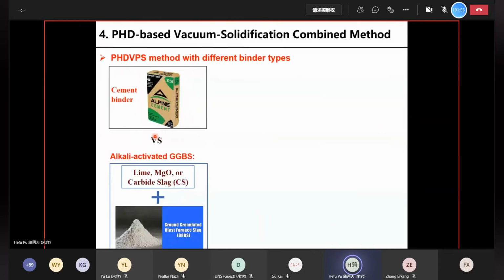We also look at different binder types. We compared the traditional cement binder with the alkaline activated GGBS, which is a ground granulated blast furnace slag. We use different types of alkalines such as lime, MgO, magnesium oxide, and carbide slag. The alkaline activated GGBS has better performance than the traditional cement binder in terms of both strength and the environmental effect. And the previous presenter, Professor Yao Lin, has done a lot of good work on this topic.